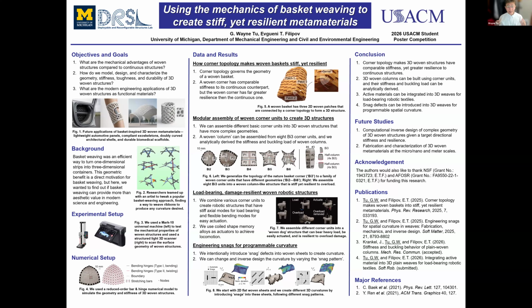So to answer that question, we first look at the geometry of a woven basket. And through our study, we found out the two-dimensional woven patches in a basket are connected by this local three-dimensional structure, which is what we call a woven corner. So this corner structure I'm holding here is the reason why 2D patches can be assembled into a 3D structure. And by further study of this woven corner structure, we found out compared to continuous corners, woven corners can provide similar stiffness, much higher resilience when it comes to large deformations, which means this woven corner here can stand extreme compressions, and after removing this load, it can perfectly bounce back and recover the initial geometry.